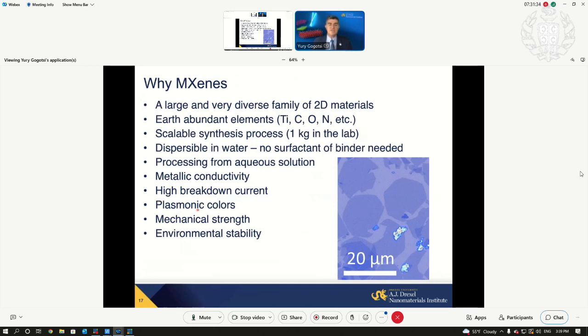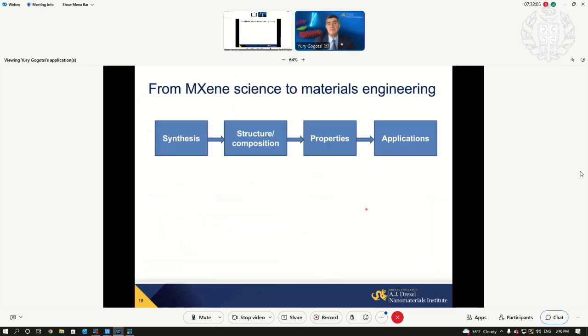They have plasmonic colors and very efficient light-to-heat conversion, and can be used from cancer treatment by photothermal therapy to water desalination using sunlight. Moreover, they are extremely strong, the strongest of all solution-processed 2D materials. That's why we can make single-layer flakes. You can see in this optical micrograph, up to 20, 40 microns in size. You cannot do this with 2D oxides. You cannot do it with the chalcogenides.